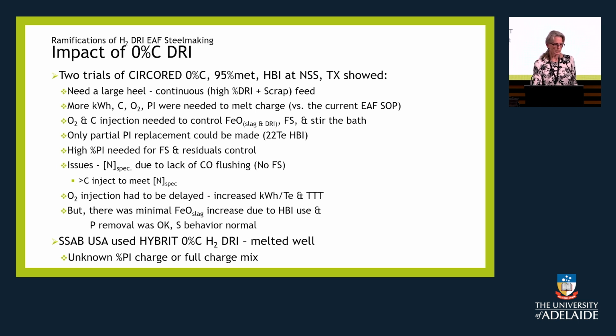There were 2 trials done with the CIRCORED zero carbon HBI that came out of Trinidad at the North Star Steel plant in Texas. Basically, they confirmed all of the thoughts that we had. You need a large heel and continuous feeding. They needed more kilowatt hours, carbon, oxygen, and pig iron to melt the charge. The oxygen and carbon injection was needed to control the FeO in the slag and in the DRI, and to stir the bath. The higher pig iron was required to help melt efficiently.